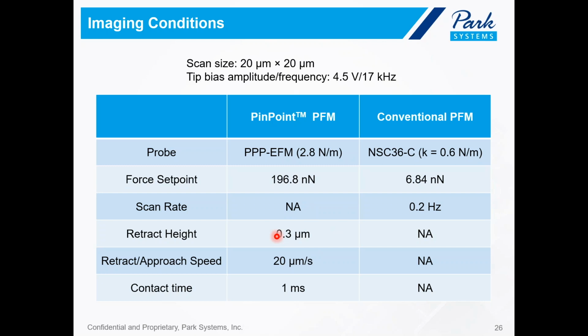If you remember when I explained the PinPoint mechanism, the probe will retract away from the surface to a safe height, a user-defined height, prior to moving to the next pixel. So this is the retract height. We have 0.3 micron here. And the retract approach speed is set at 20 micron per second. The contact time between the probe and the sample surface was controlled at 1 millisecond. And again, this value can be adjusted or tailored to the sample as needed.